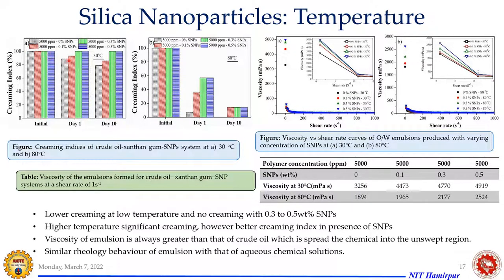Okay, and if you see on day one, you can see this is the creaming behavior. So the part when we are having no particles, it shows some creaming behavior, whereas when there is nanoparticle, there is some creaming behavior, but it is almost negligible. As we reach day 10, you realize at 0% and 0.1% nanoparticle, there is some creaming, but at 0.3% and 0.5%, beyond that, there is no creaming. So this shows that 0.3% and beyond could be the concentration that we can select, so that you can have this stable emulsion.